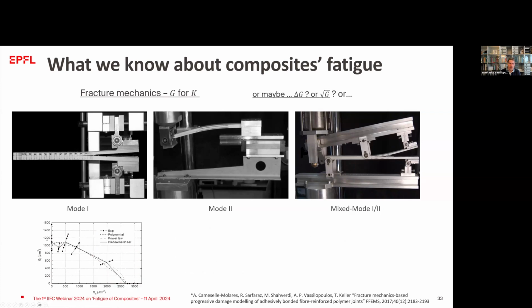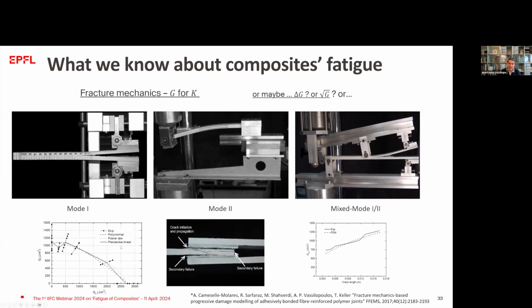So we also used multi-axial failure criteria in this case, and we can investigate the behavior of joints from the same materials as those that we tested in mode 1, mode 2, and mixed mode. And we can estimate for these joints the behavior of the G propagation during the loading, or this can be also extended for fatigue loading and investigating the behavior of this joint in fatigue. So creating actually an FCG curve for the joint.